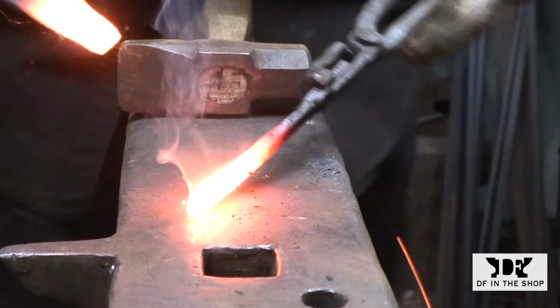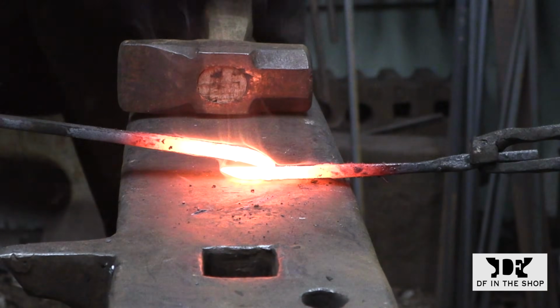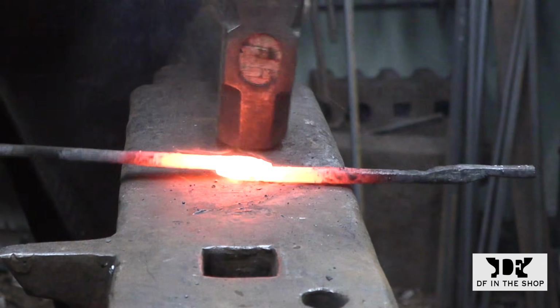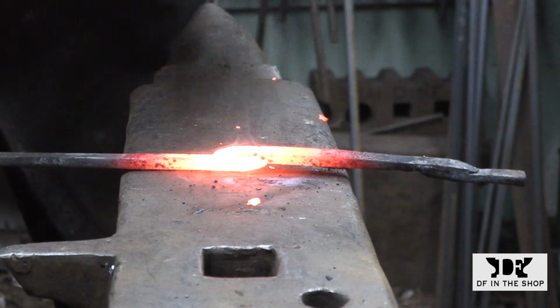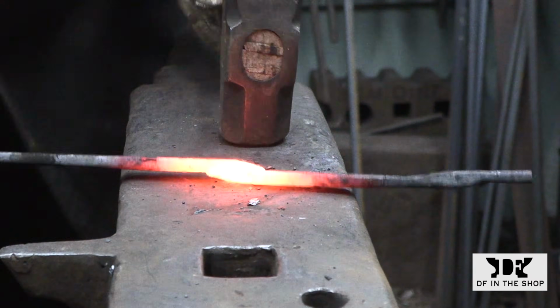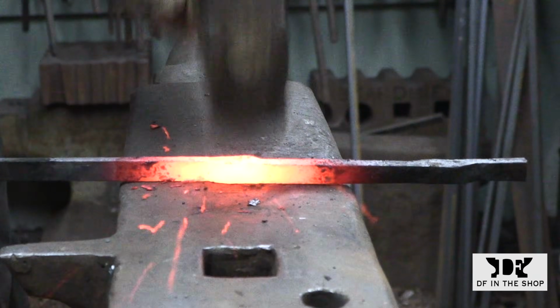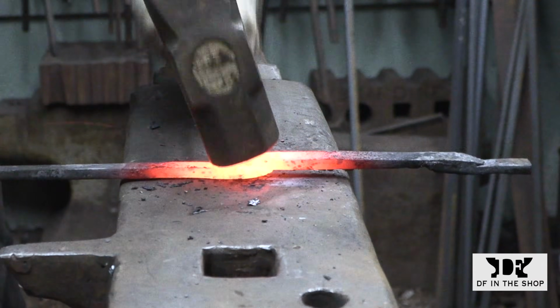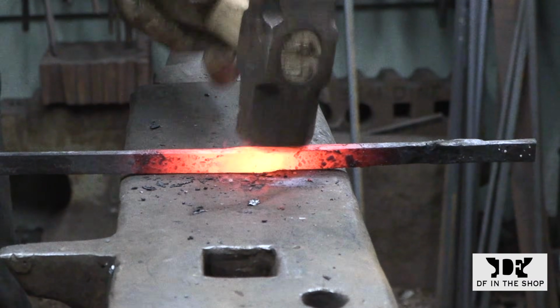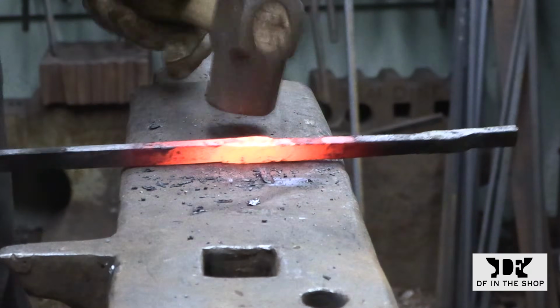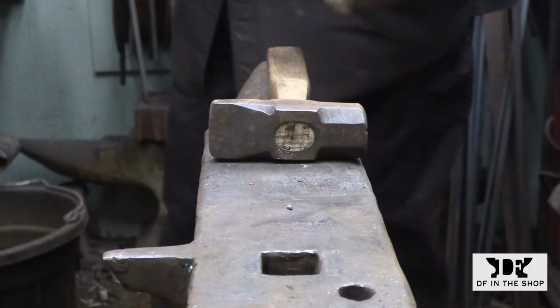So here you can see that I had a fleeting moment of coordination and I was able to set a weld with a much shorter overlap than I did with the first weld. And that's going to allow me to get a lot more work done in this heat. I was able to tack the weld and set both scarves in one operation. This is a good length for this weld, so it's what you're aiming for.